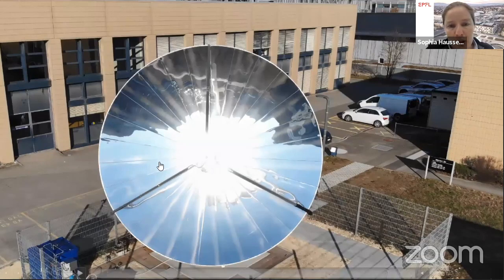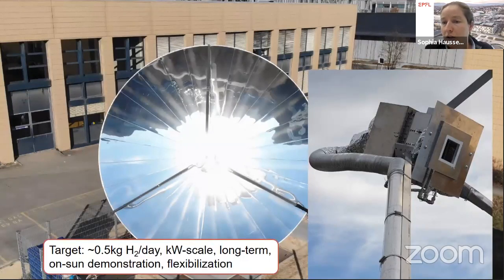This parabolic concentrator has a diameter of 7 meters, and in the focal spot, we put our solar reactor. And so here you can see this integrated photoelectrochemical system. The photoactive area is now 12 by 12 square centimeter, and we're operating at about 900 concentration.